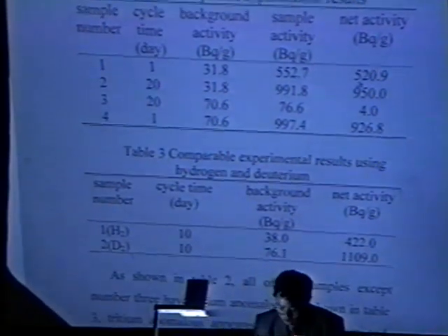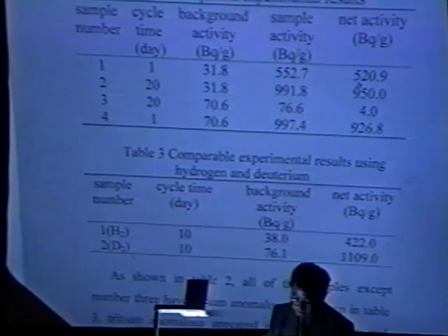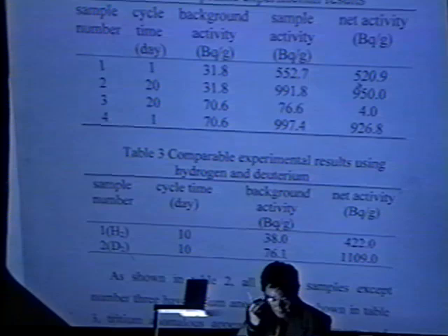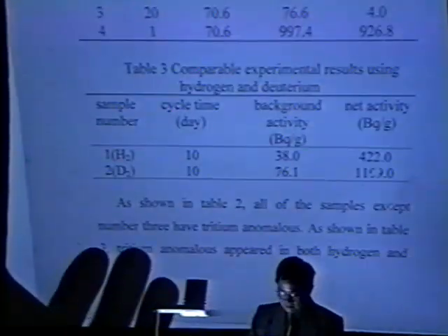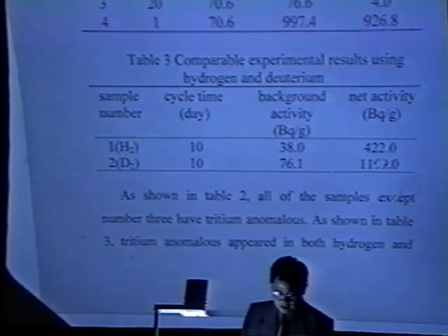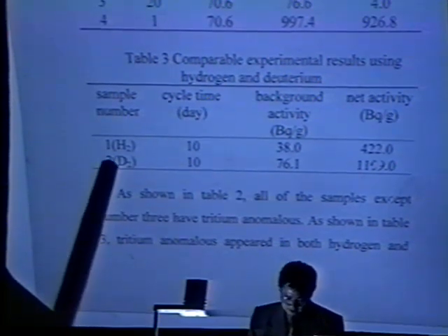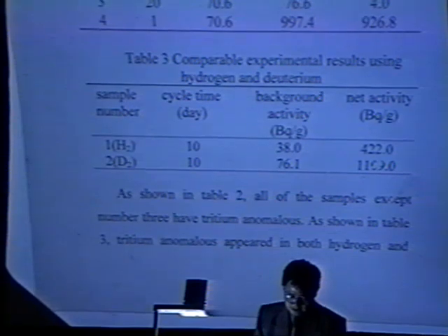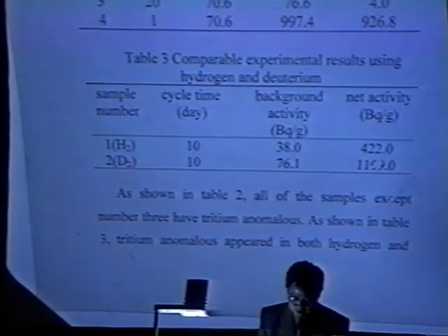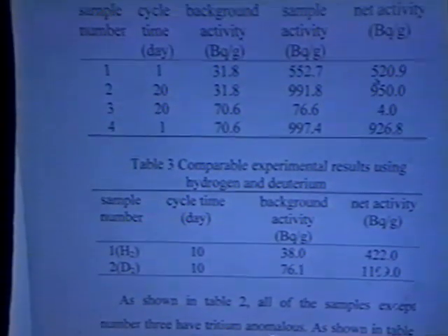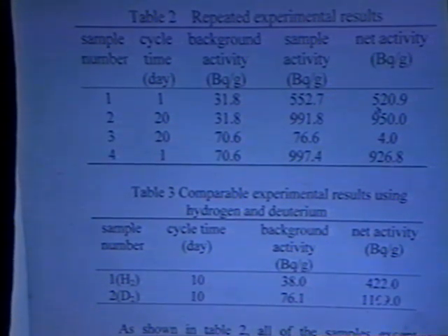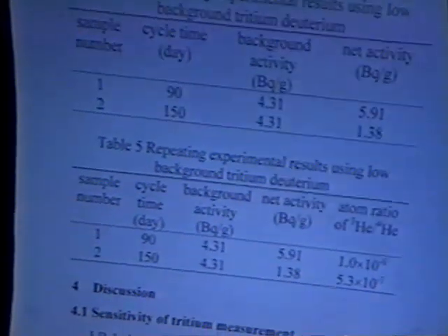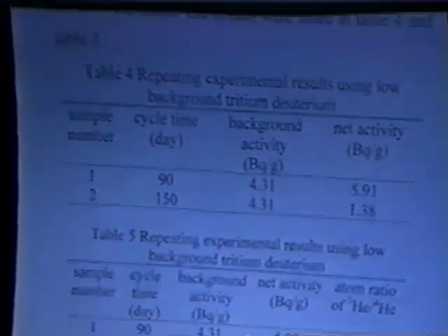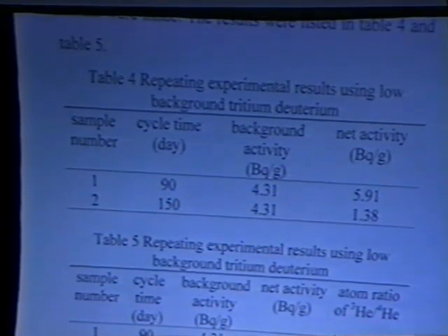Table 2 is repeated experimental results using palladium plated diatomite. From this table, all of the samples except number 3 have tritium anomalous. Table 3 is comparable experimental results using hydrogen and deuterium gas. From this table, we can see both the hydrogen palladium system and the deuterium palladium system, they exist tritium anomalous, using low background tritium deuterium.